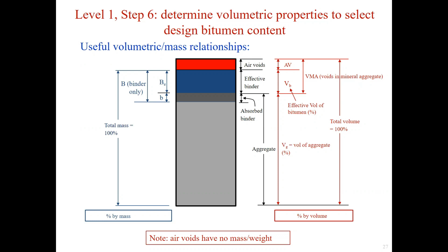From a volume point of view, AV is the volume of air voids, and VB is the effective volume of the bitumen. The sum of them is called VMA, the voids in mineral aggregate. Typical values of VMA in dense mixes can be 13% to 20%, depending on the nominal size of the mix.